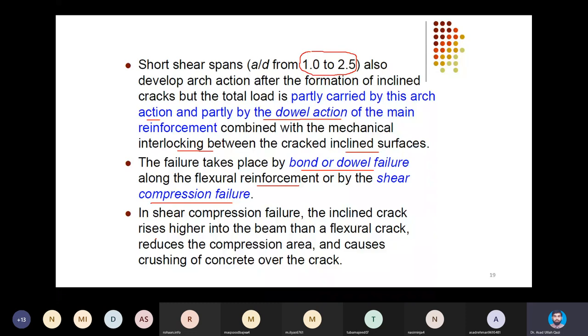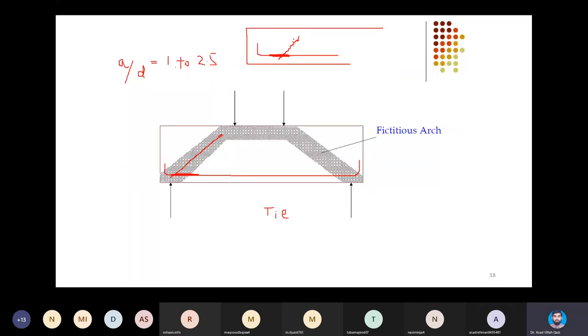What this shear compression failure means is that in such beams, once the crack moves further up, your compression area is reducing. With the diagonal crack moving up, don't forget that you also require C equal to T to get that internal couple between steel and concrete in case of flexural resistance. So when the crack is moving up, your compression block is reducing and eventually crushing will take place at this position when the crack has almost consumed the compression block. So we call it shear compression failure. The cause was the movement, the propagation of the diagonal crack, and consumption of the compression block.